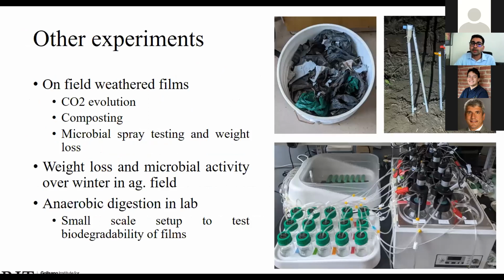Some other experiments we are looking at are based on the on-field weathered films, which Kirby Farms is helping us with, which we set up in the Kirby Farms. We want to do a CO2 evolution test just to see if these biodegrade better than the pristine films, and that kind of proves the point that as these films are weaker in mechanical properties, bonds are easier to break. It may be that the evolution of CO2 is faster, or there's no lag phase, or we see a very little lag phase as compared to pristine films.